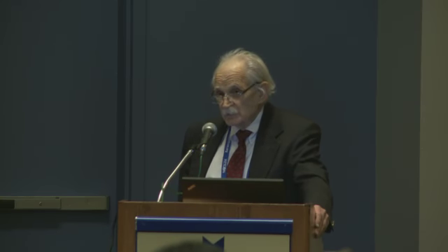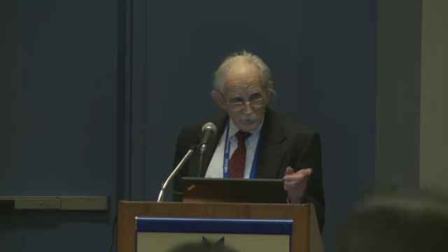Yeah, there's another part of this talk which I threw out because one obvious question which somebody is probably going to raise is that tin 4, tin 2 looks pretty lousy as a redox couple for a battery. But in fact, if you go up to 9 molar or 10 molar bromide, that really collapses a lot. So yeah, bromide really helps in that.